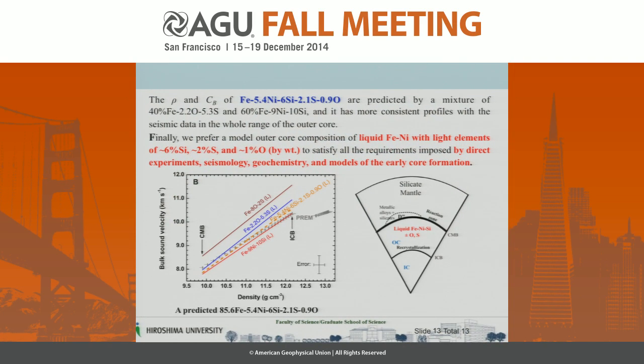We also predict an iron-5.4-nickel, 6% silicon, 2.1% sulfur, and 0.9% oxygen composition by a mixture of the iron-oxygen-sulfur and iron-nickel-silicon systems. And this is the predicted bulk sound and density relationship. It has more consistent profiles with the seismic data in the whole range of the outer core.